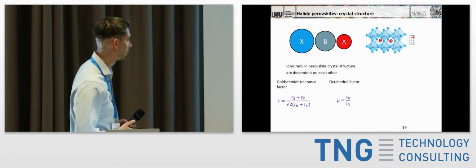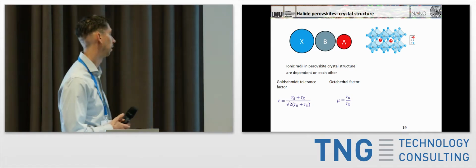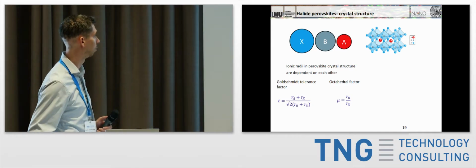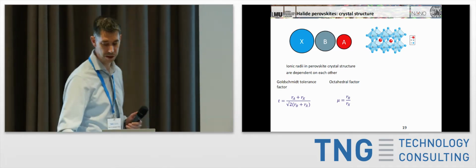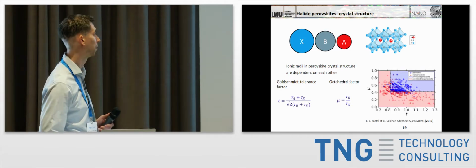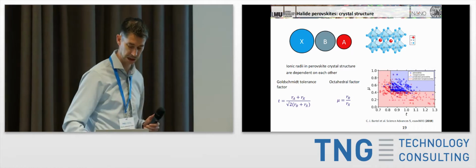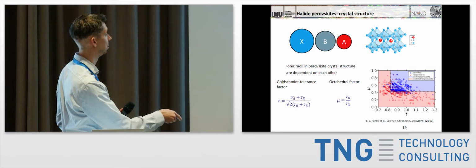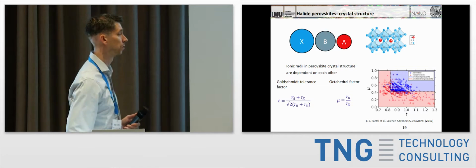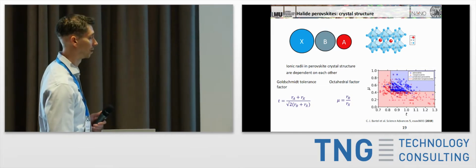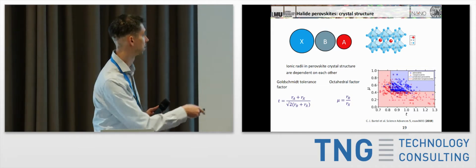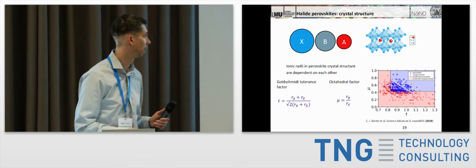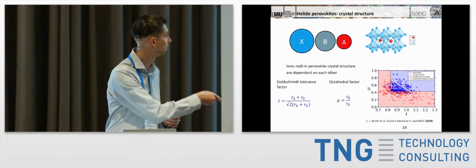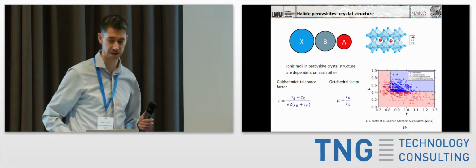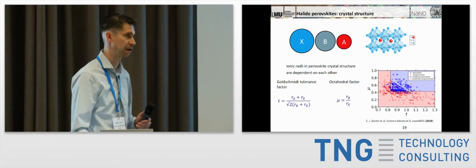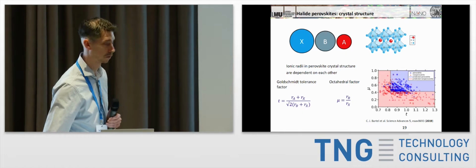There are 2 factors that take into account the radii of these materials, the Goldschmidt factor and the octahedral factor, that basically give us a range of tolerance factors for where these perovskites can exist. And so there's essentially just plotting these 2 factors versus each other with a predicted range where all of these materials are stable. And you can see it's only more or less a very arbitrary number, as there are some materials that sit in this region where perovskites shouldn't exist that do, and the other way around. We also have materials that should exist that don't. So it's a very arbitrary science in which of these materials actually work and form stable perovskites.